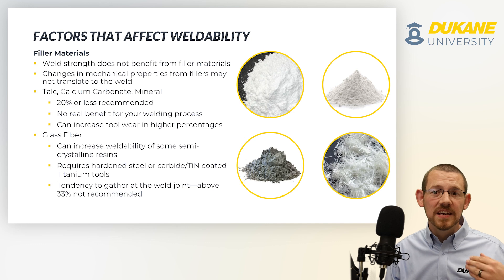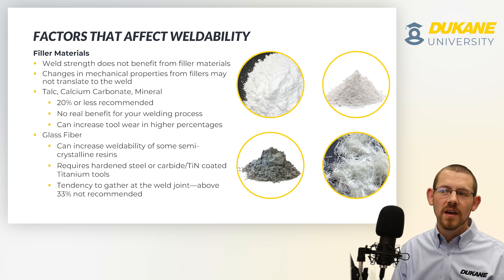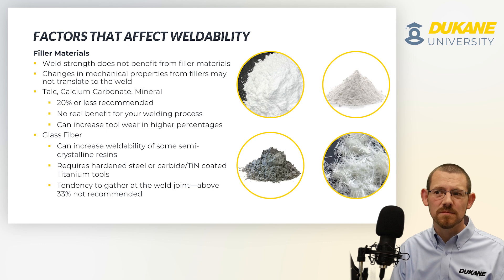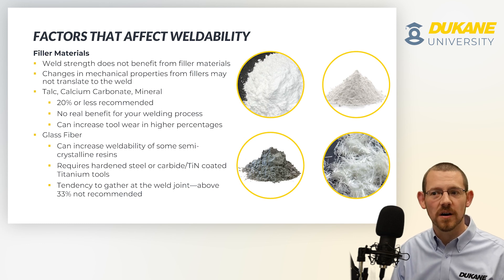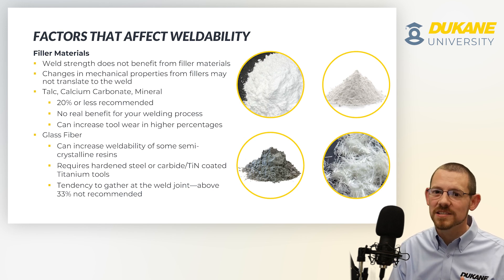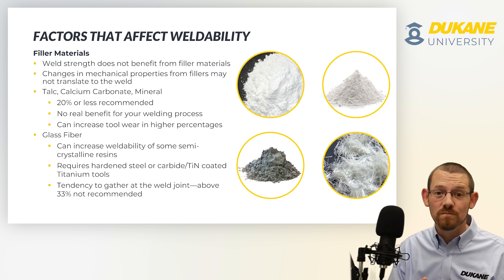The next thing that might affect your weld is filler materials. Generally, weld strength does not directly benefit from having a filler material in your part. Commonly, people will put things like talc or calcium carbonate into their parts to reduce the amount of resin. Ultrasonic welding can handle that, but we recommend keeping fillers to 20% or less. Your weld strength is a resin-to-resin chemical bond only — anything in that joint that is not plastic is not helping you. And if you're using a high percentage of mineral or talc, you can actually start degrading the surface of your sonotrodes.